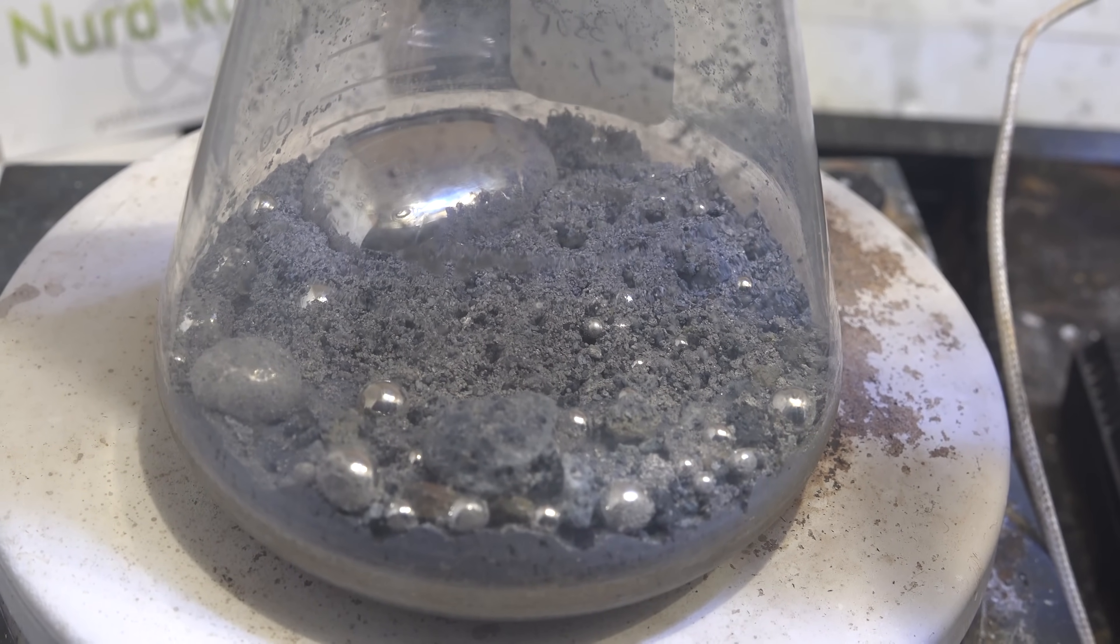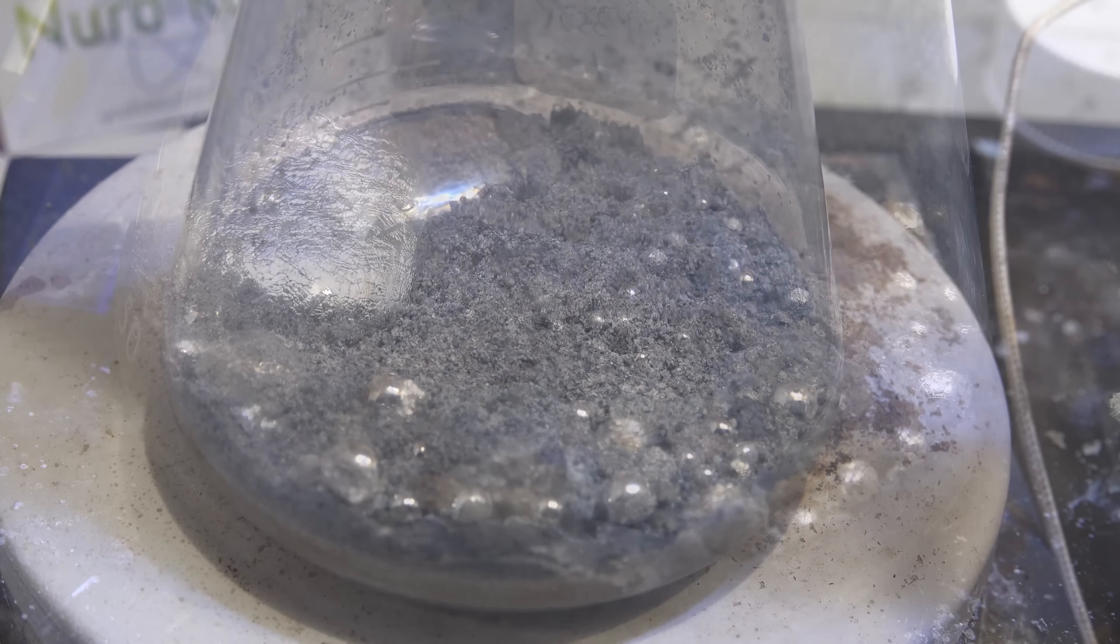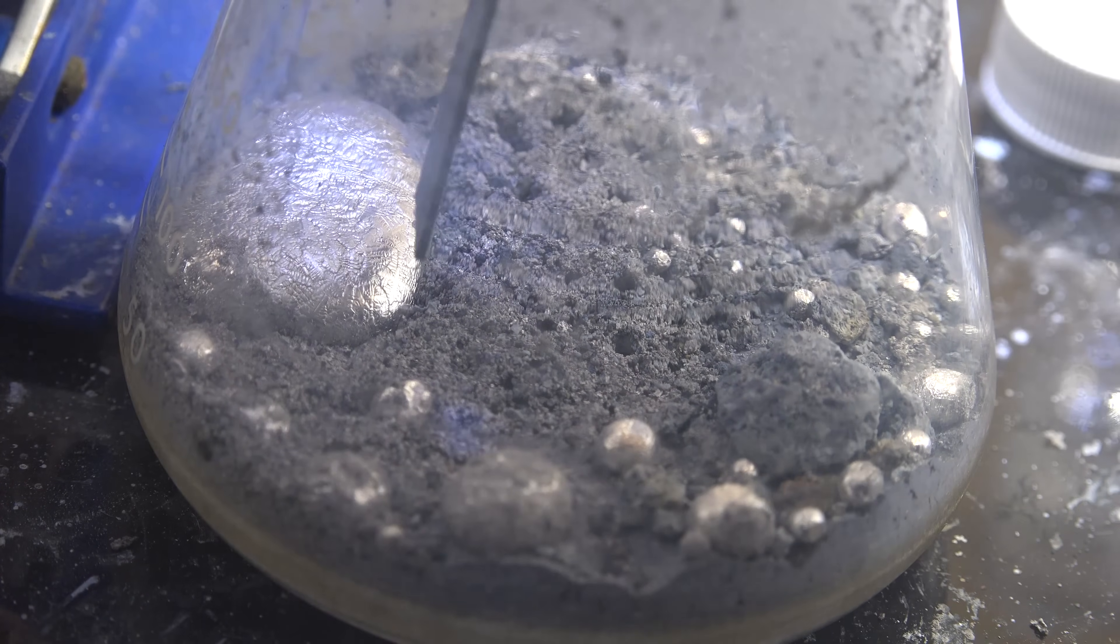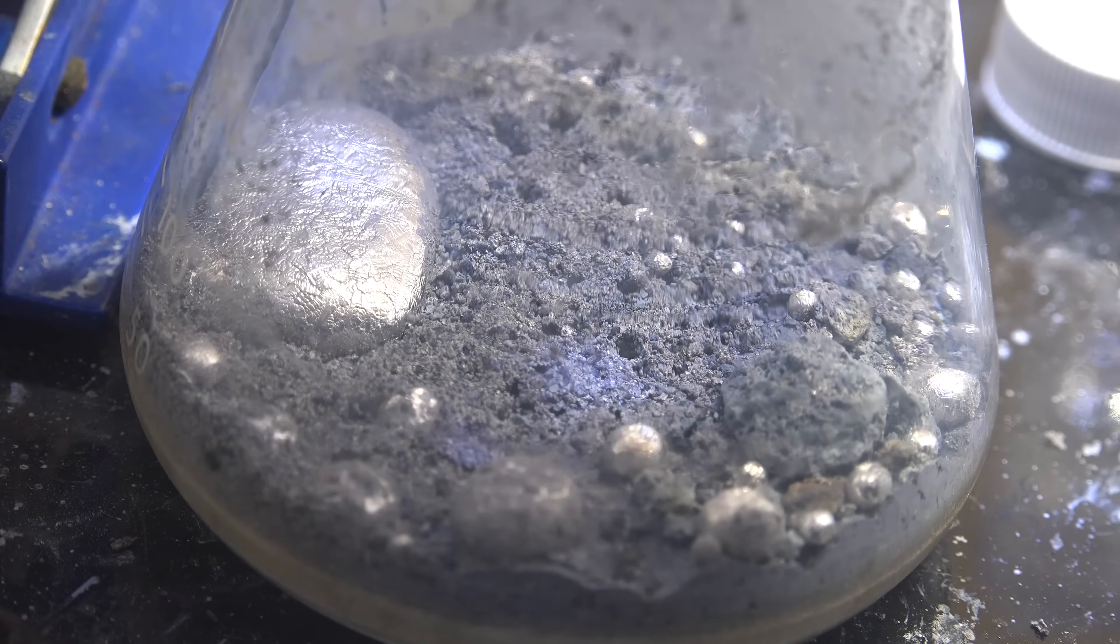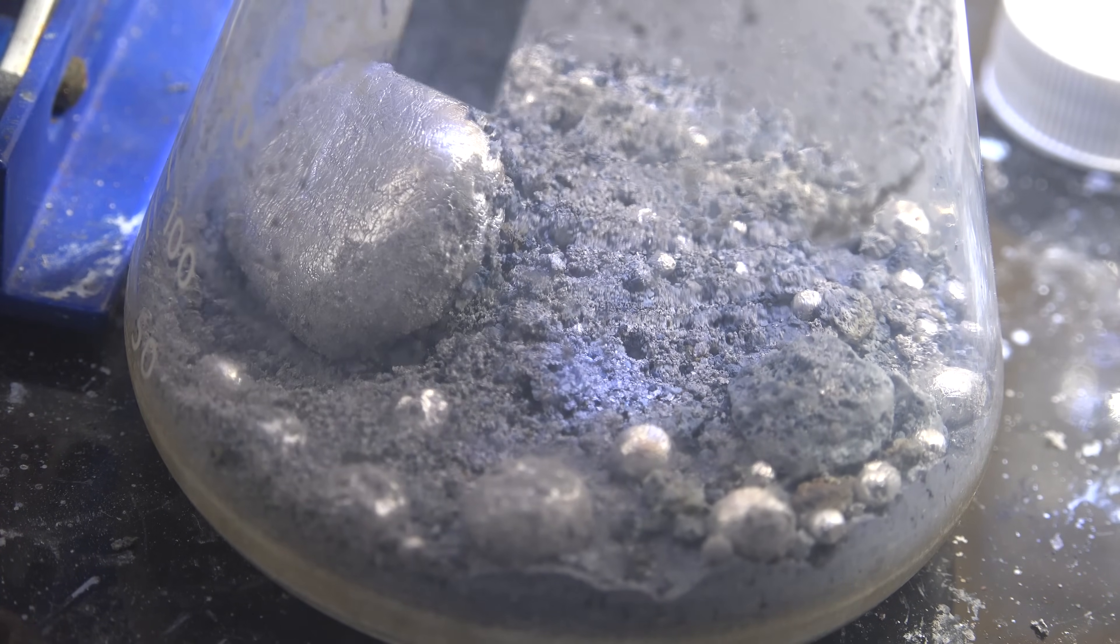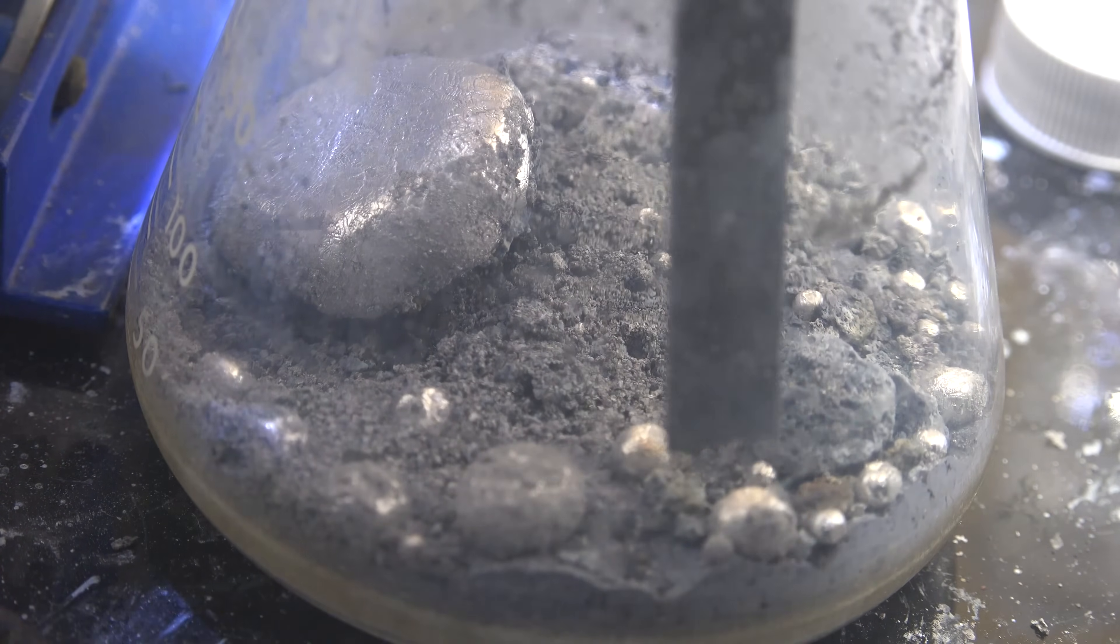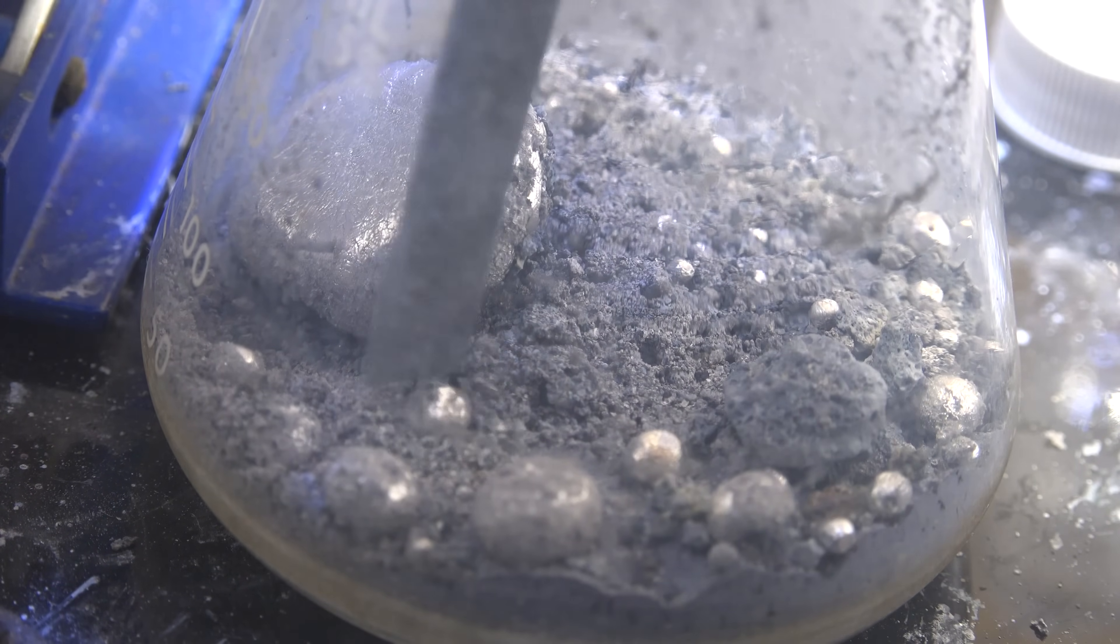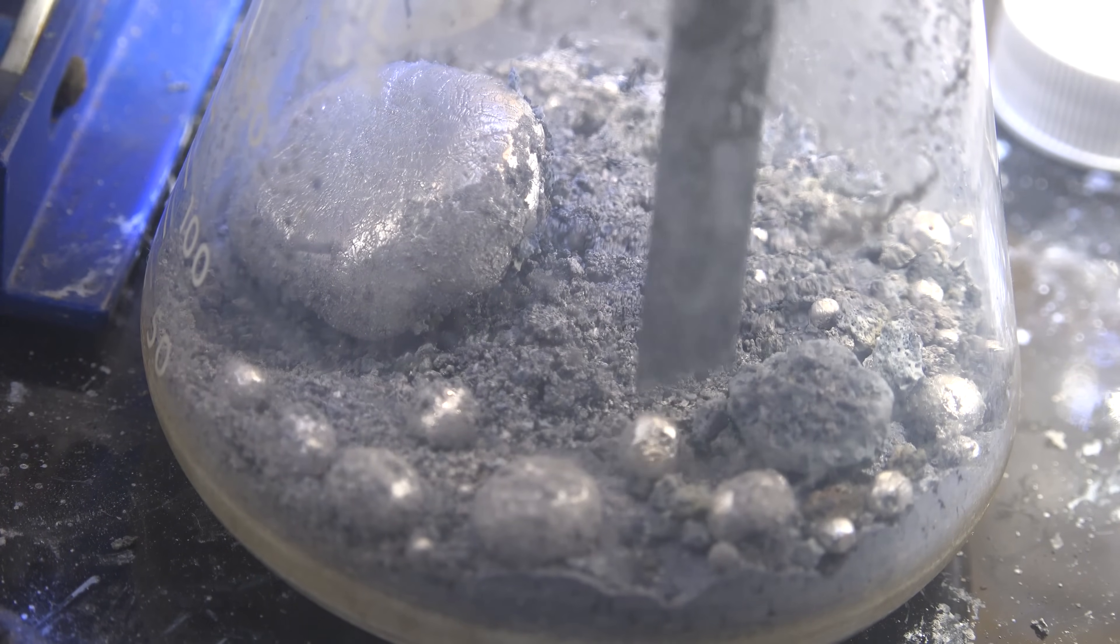Anyway, turn off the heating and let the sodium solidify. And here we are with the sodium at room temperature. Now slip in a metal strip or stirring rod and dislodge these sodium nuggets. The reason why I let the distillation go dry is that it makes the slag of magnesium oxide cake together instead of remaining as a powder. This makes it much easier to separate and only a small amount of slag will come out when we pour out the sodium.